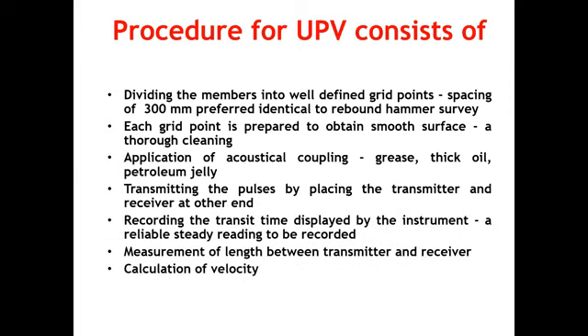For example, I wanted to do rebound hammer and UPV in many places, but I'll not be able to do cores. The number of cores cannot be much more. So what you can do is take about 9 or 10 cores, and then take rebound hammer numbers and UPV, and take this as a base data. At the rest of the other places you do the rebound hammer and then UPV, and then you'll be able to use this as a correlation. Yes, the grade of concrete or fck value of the concrete may be expected to be obtained this way.